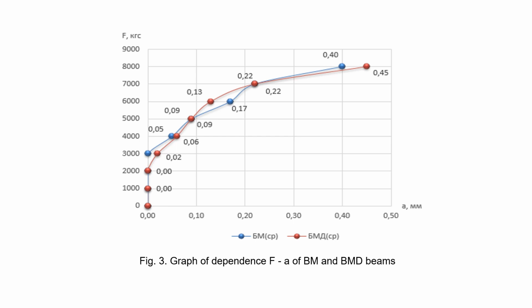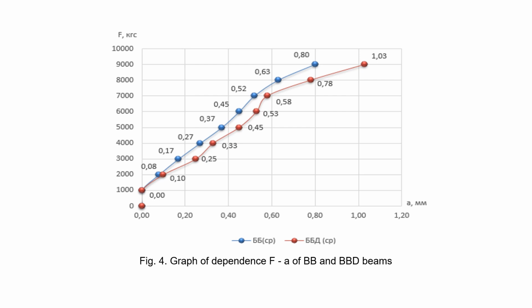The beginning of reinforcement yield was recorded at a load of 0.9 of the destructive load, which caused the destruction of the beams with the compression of the concrete. The beams with basalt-plastic reinforcement of the BB and BBD series showed the largest values of the width of normal cracks, which is explained by the lower elastic modulus of the BFRP reinforcement itself.